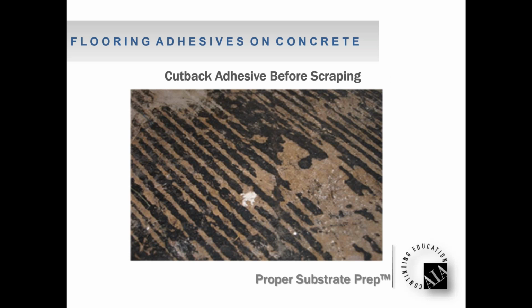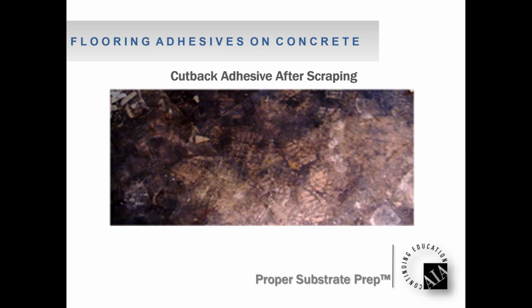Here's a picture of cutback adhesive after some VCT was removed. You can still see the thick buildup of adhesive from originally combing that out. Bottom line is you want to scrape it down to a thin residue. And yes, there are some dust footprints in this picture, and you've got to remove the dust, but nonetheless, adhesive has to be scraped down to a thin, well-bonded residue, like a stain on the floor. Okay.